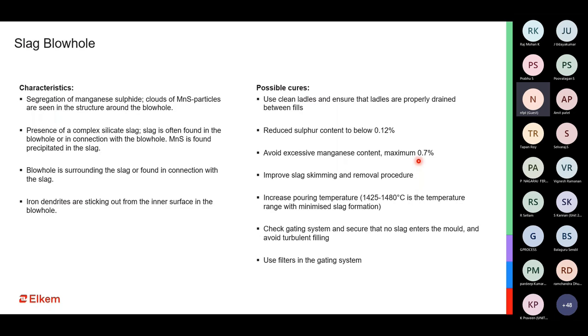This goes in general for any kind of defect in cast iron, that we have to make sure that our temperatures are sufficient and as per the requirement of the casting, and we should not go either too high or too low when it comes to the operating temperatures. We also have to design our casting and our methoding and gating system in such a manner that we do not have turbulence when the metal flows from the downsprue into the running system, to the ingates and into the casting. Thereby, you do not have any excessive metal and atmosphere interaction, and thereby you do not have much oxidation.